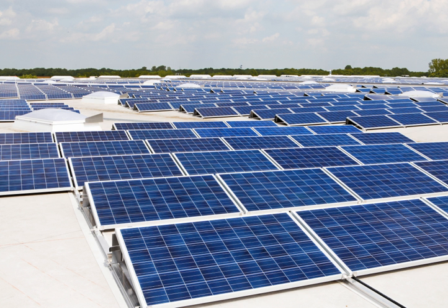Research by Imperial College, London has shown that the efficiency of a solar panel can be improved by studding the light-receiving semiconductor surface with aluminum nanocylinders similar to the ridges on Lego blocks. The scattered light then travels along a longer path in the semiconductor, which means that more photons can be absorbed and converted into current. Although these nanocylinders have been used previously, aluminum was preceded by gold and silver, where the light scattering occurred in the near-infrared region and visible light was absorbed strongly.